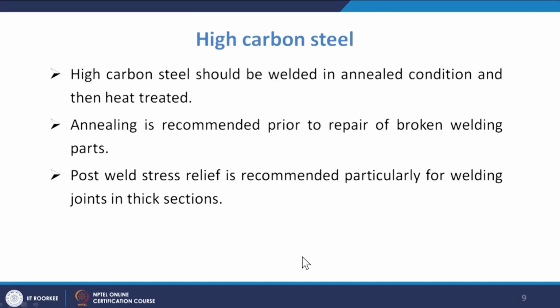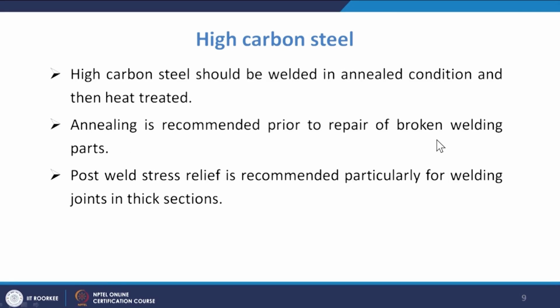Okay, so high carbon steel should be welded in an annealed condition and then heat treated, and annealing is recommended prior to the repair of broken welded parts. Okay, post weld stress relief is recommended particularly for welded joints of thick sections. As we said, if the carbon content increases, we have to use a much higher preheat treatment temperature.